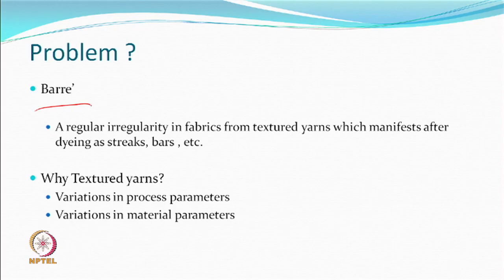Then, this material that we are using is a material which has been drawn before. So, if someone has made some difference in the drawing conditions, that also will get added up. So, you have a material which you always thought is a fully drawn yarn, it has got the same property, it has got the same denier, it has got the same number of filaments, looks same, but the morphology may not be same. A fully drawn yarn is not a product which has only very specific properties with specific values, but they have a range. And because they have a range, and then you are again doing texturing, so there is a thermal history, there could be a stress induced crystallinity which happens during drawing, that could be history. Then you have certain materials like polyester which are drawn also at a little higher temperature, and so they have a history.